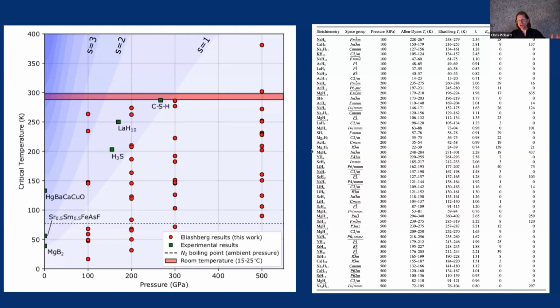But generating this large number of structures allowed us to do something rather nice, which is to plot a distribution of these structures with pressure. And what was very nice was that we could see, okay, so you go to very high pressure, some of the structures have very high TC. But also, as you go down to lower pressures, the TC was not dropping too dramatically with pressure, which has given hope. And I mean, we're not the only ones. There's quite a bit of a gold rush at the moment going on to try and find lower pressure but high TC superconductors.